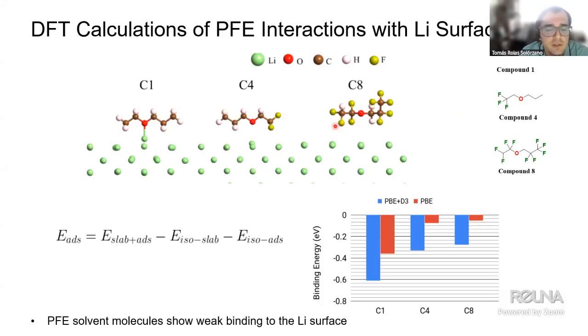So the typical process in this case is to calculate the energy of the system as a whole, meaning the molecule plus the surface. Then we calculate the energy of just the surface isolated and the energy of just the molecule isolated. We calculate the difference, and the remaining energy will be just the energy of the interaction between molecule and surface. And that energy tells us that as you increase the fluorination, you are decreasing the energy with which it attaches to the surface, which is what we call the binding energy. So it progressively shows weaker and weaker interaction.